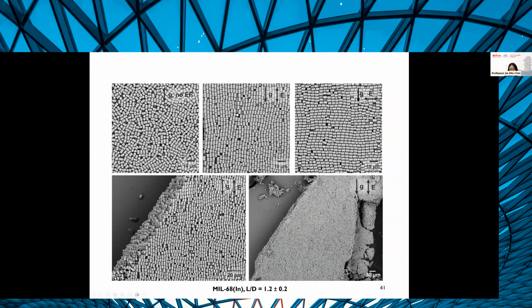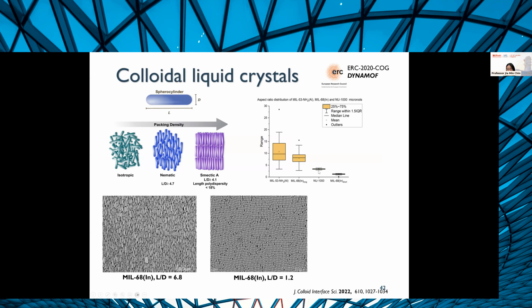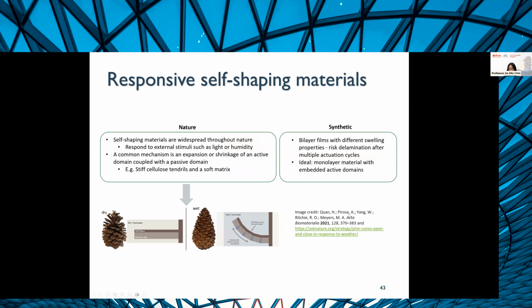Now, if you move on to an even lower aspect ratio of 1.2, which is easily achievable for a lot of different types of MOF crystals, we saw that we still get a very strong preferred orientation, as you can see here, and very easy assemblies. We can get this in about 10 to 20 minutes without any issues. So with this, I've showed you that through the whole range of aspect ratios shown here, we can really control MOF orientation and packing. And we can do this across almost centimeter scale assemblies.